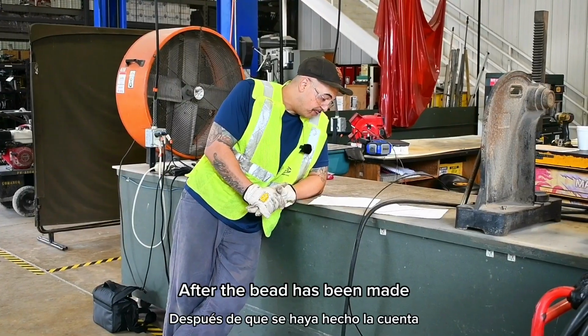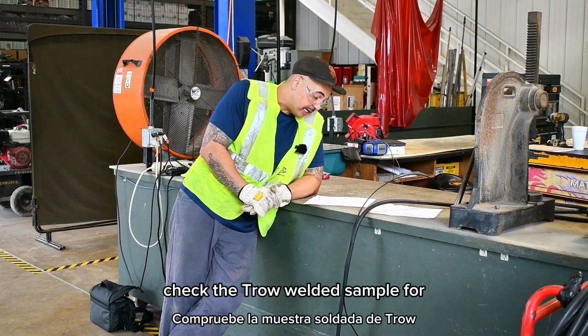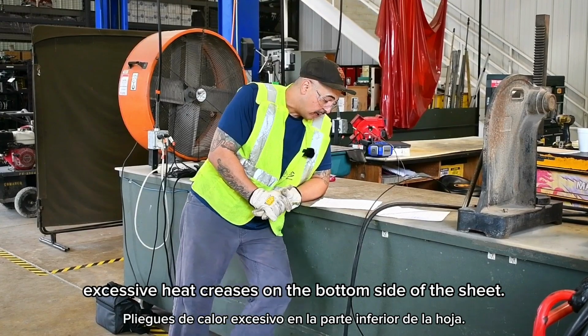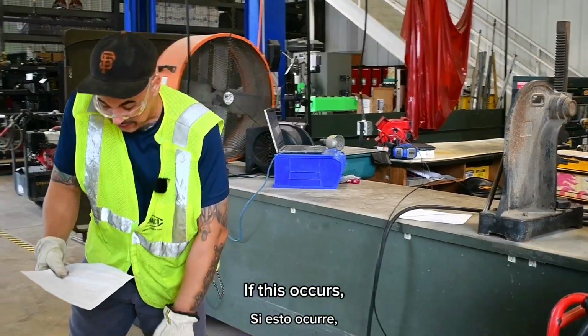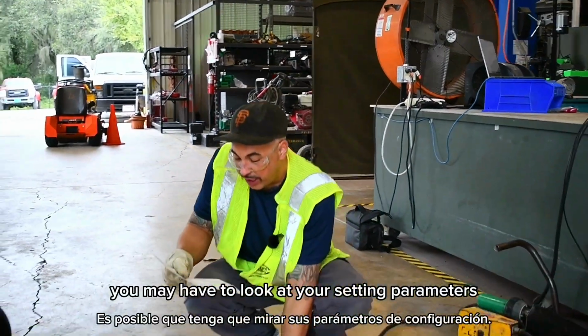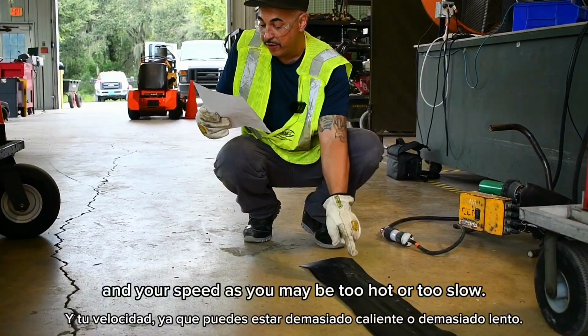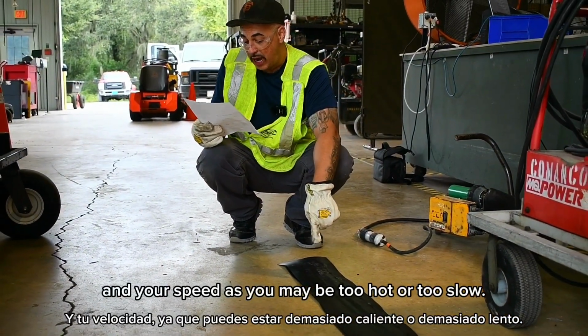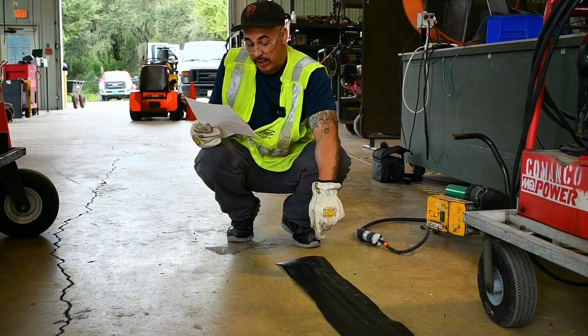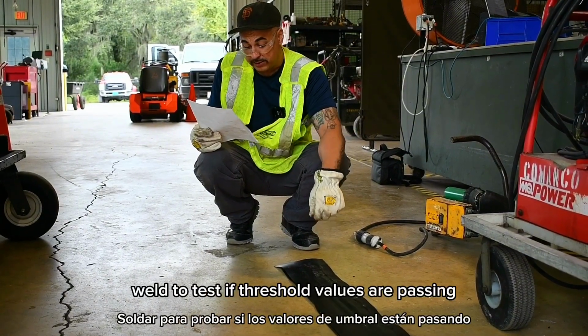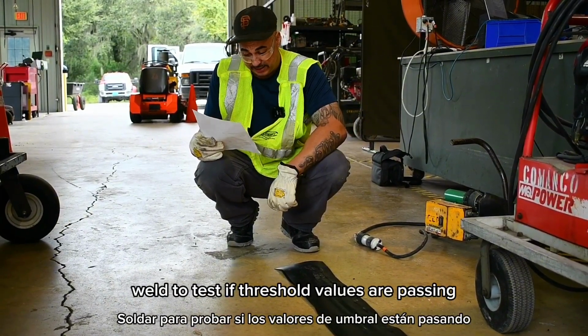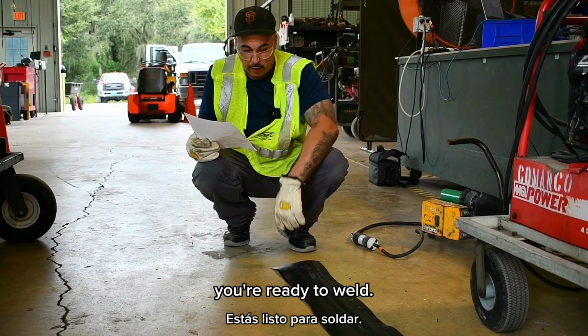After the bead has been made, check the trial welded sample for excessive heat creases on the bottom side of the sheet. If this occurs, you may have to look at your setting parameters and your speed, as you may be too hot or too slow. Cut a sample of your trial weld to test if threshold values are passing, and if they are, you're ready to weld.